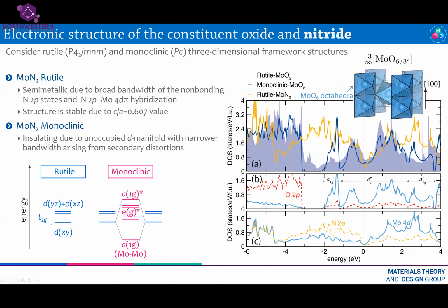But now we can look at the nitride end member. So this is moly nitride. And nominally moly nitride in the rutile structure is a semi-metal. So it has a very small number of states at the Fermi level. That's what's shown down here. And if you put in the monoclinic distortion, it prefers to have the monoclinic distortion, it will be insulating, as you would expect.